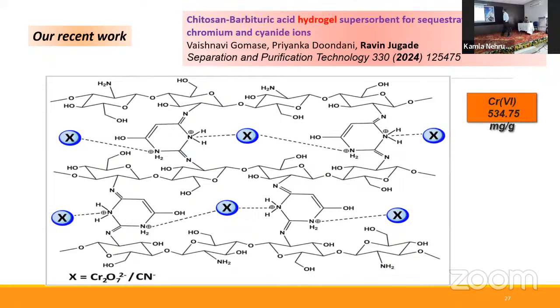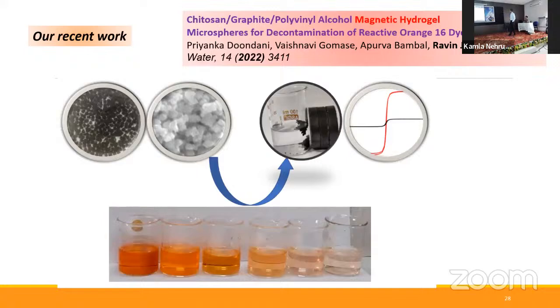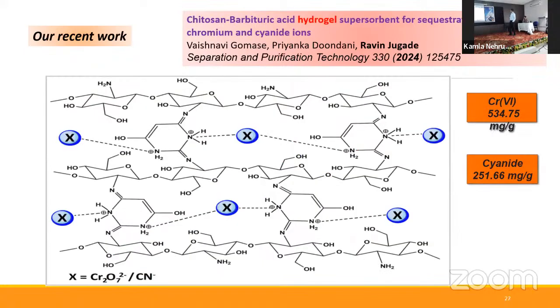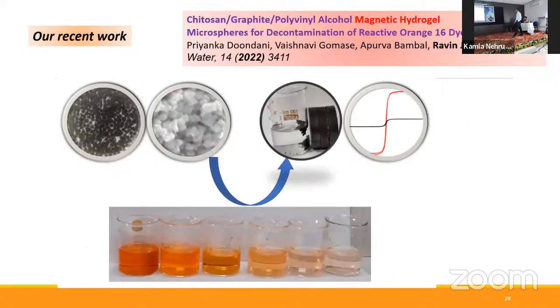Yes, recently we have reported this chitosan barbituric acid. It's again a nitrogen functionality introduction into the chitosan matrix for the removal of chromium as well as cyanide ions. Recently published in 2024. It is in the form of a hydrogel. Again, a physical modification.